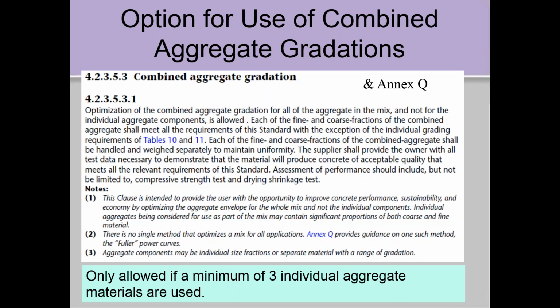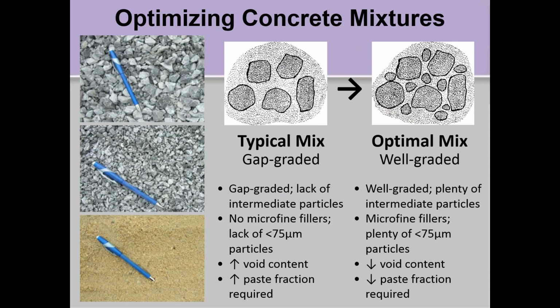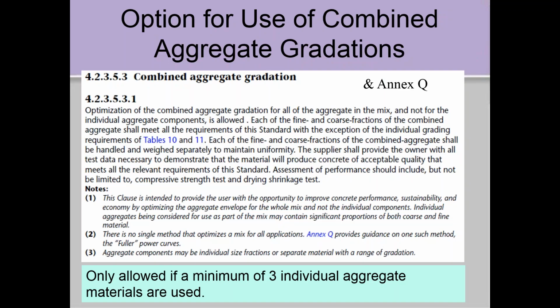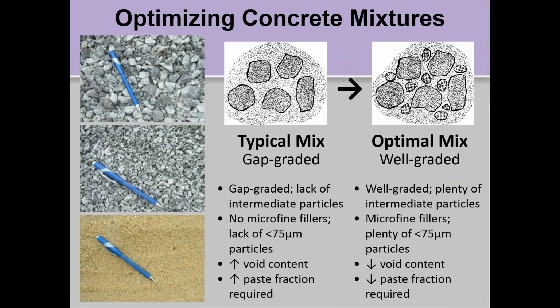And it's in section 4, again, combined aggregate gradations. It's also an example given in Annex Q. And you basically optimize the whole gradation of the aggregate. And then for testing purposes, you split it on the 5mm sieve, and you test everything above 5 as a coarse aggregate, everything minus the portion that's -5 as the fine aggregate. So often this can be done just by fitting an intermediate material, even waste chip materials, that fills that gap between the fine and coarse aggregates, so you get better packing of the aggregates.